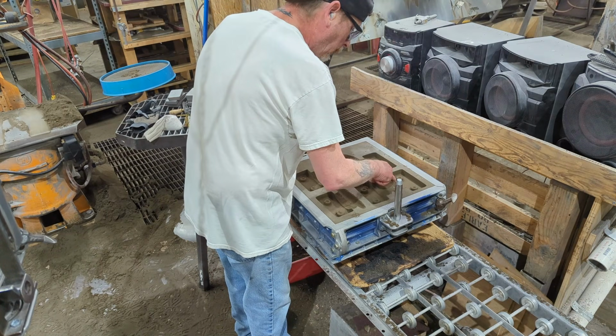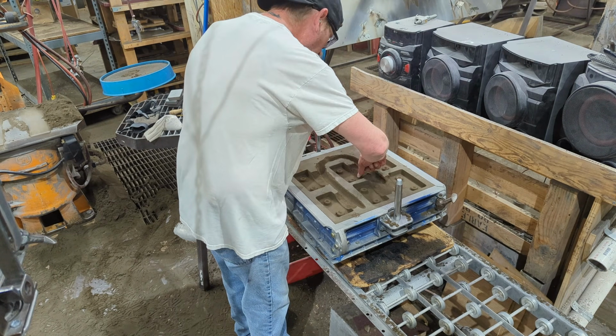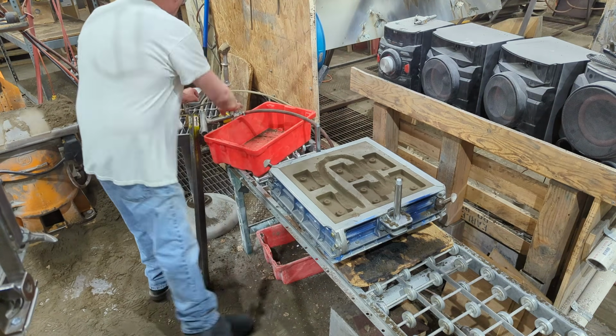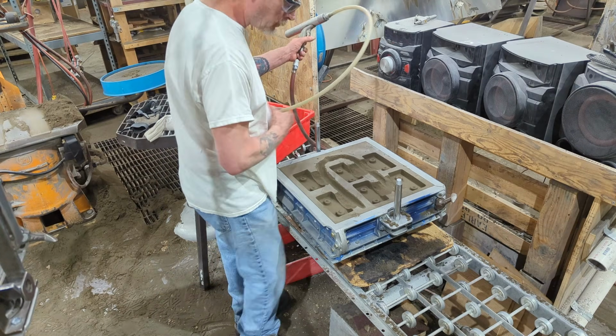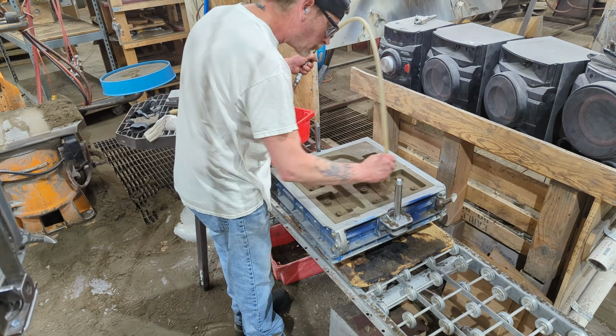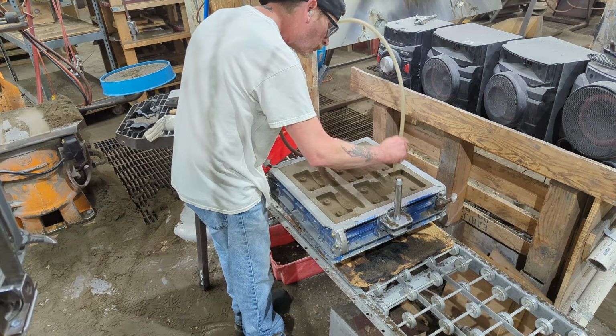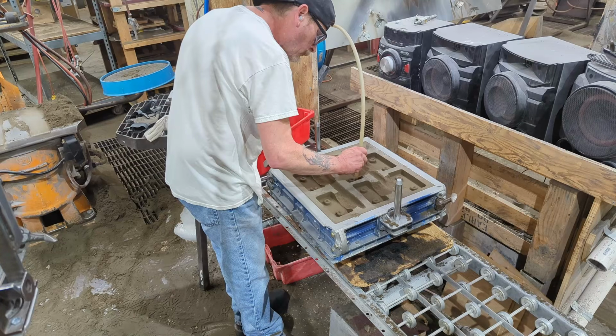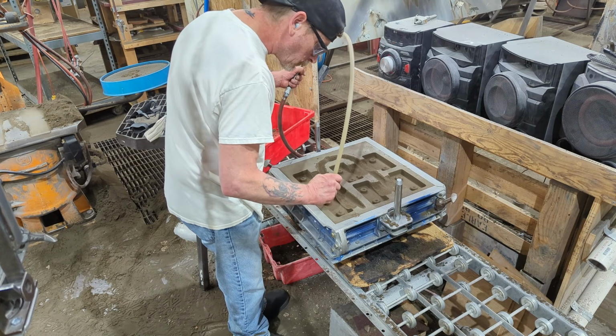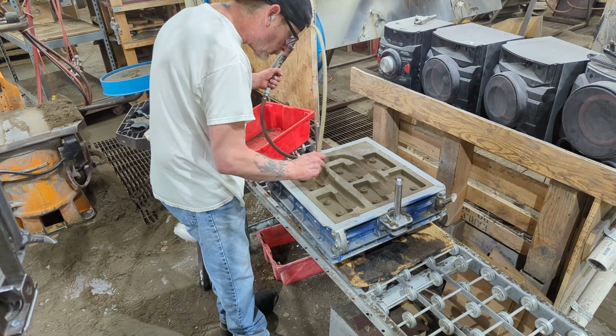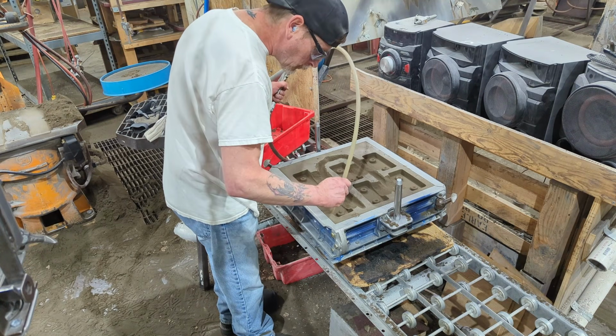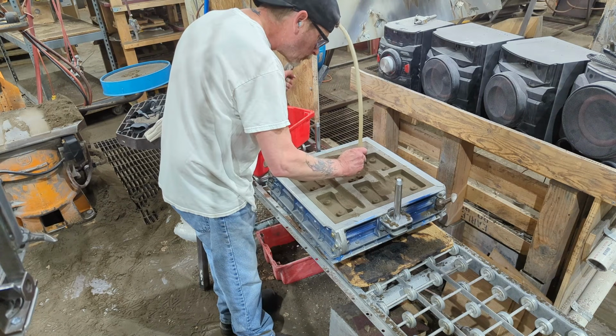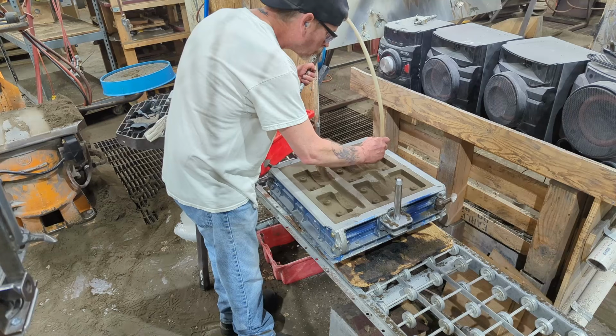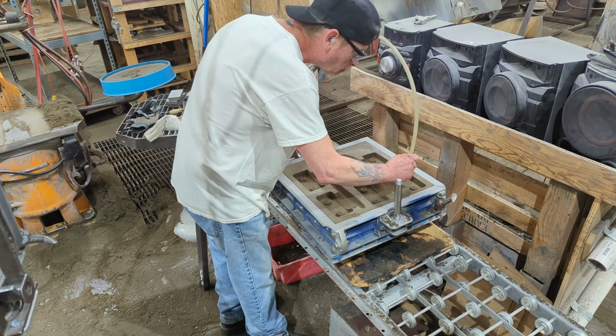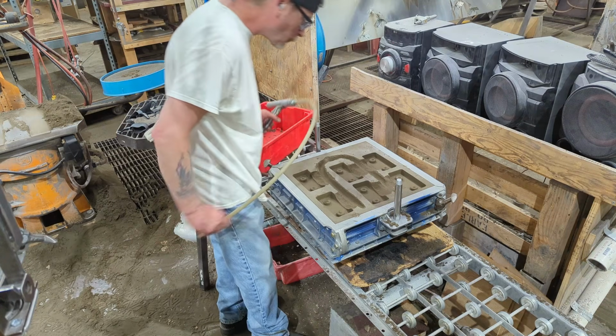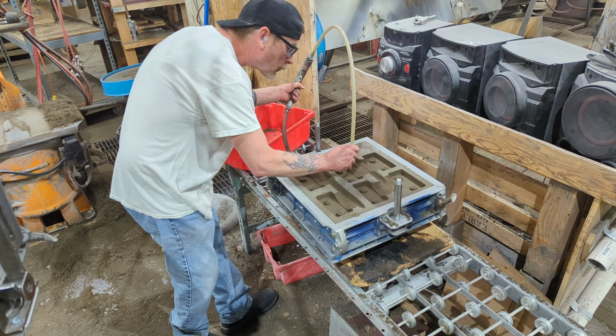Chad now smooths all of the hand-carved gates and runners, removing any sharp ridges or excess sand. He then uses a small pneumatic vacuum to remove every last loose grain. Even a single loose sand particle can be swept into the molten metal stream, causing a void or rough spot in the finished casting. This can create an imperfection in the final part, or can create an irregular surface finish, which is unacceptable for these precision components. Chad's thoroughness here reflects the level and care we put into every mold we make.